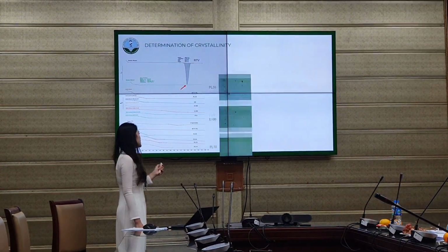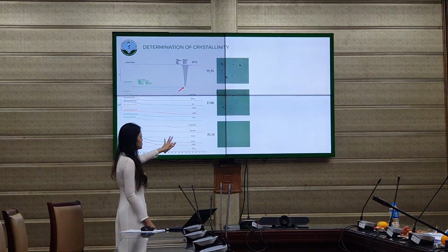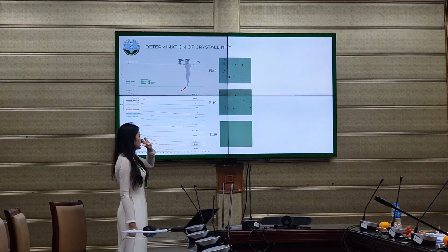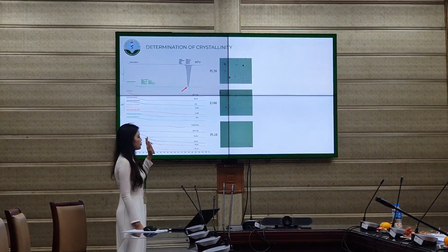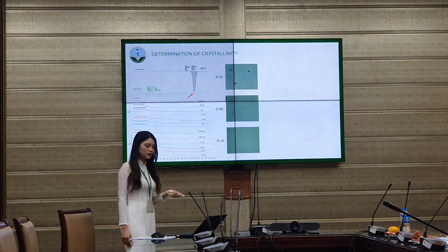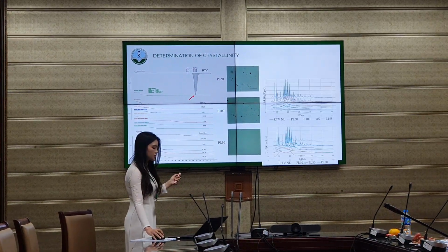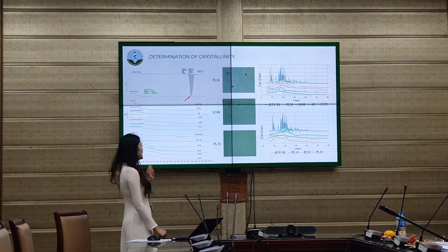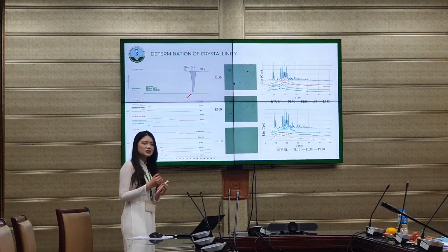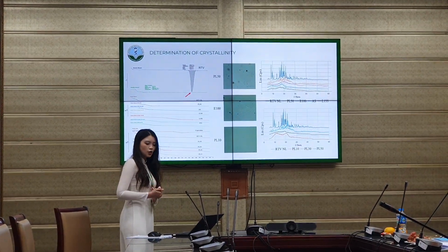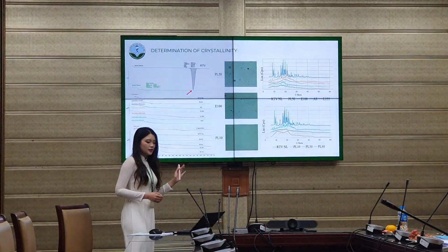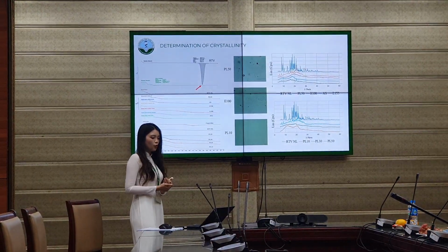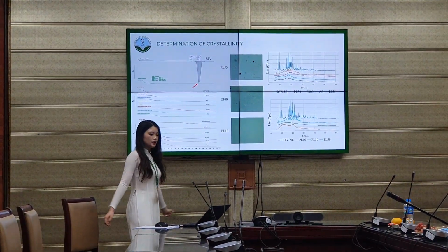However, the microscopic images revealed that while some samples show no visible crystal structure, there are still some samples that have crystal formation, such as PL50 and E100. Therefore, the XRD results serve as a more reliable confirmation of crystallinity. During the DSC analysis, the thermal input can cause partial dissolution of the drug, potentially leading to misinterpretation. XRD measurement preserves the original solid state of the sample, offering higher accuracy in detecting crystallinity.